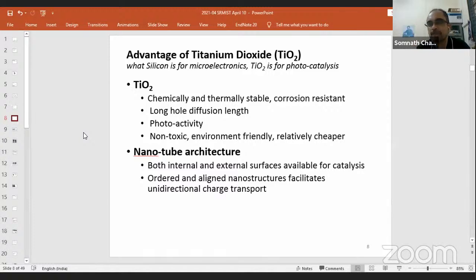We use talcum powder in the summer. Chennai, summer has already come. This talcum powder has titanium dioxide, zinc oxide. The sunscreen lotion is almost fully titanium dioxide or its composite. Why? What is the role of sunscreen lotion? It actually needs to absorb the UV light, right? So TiO2 absorbs UV light, 3.2 electron volt. So, one of the best things.